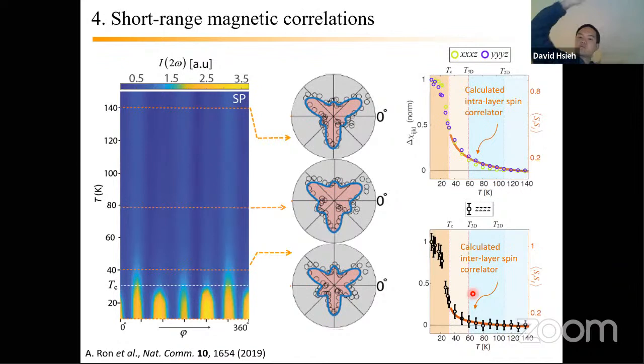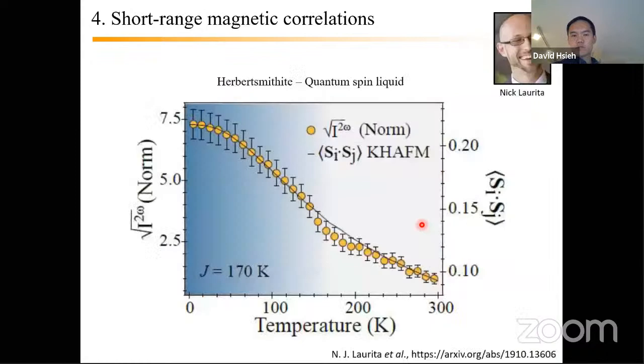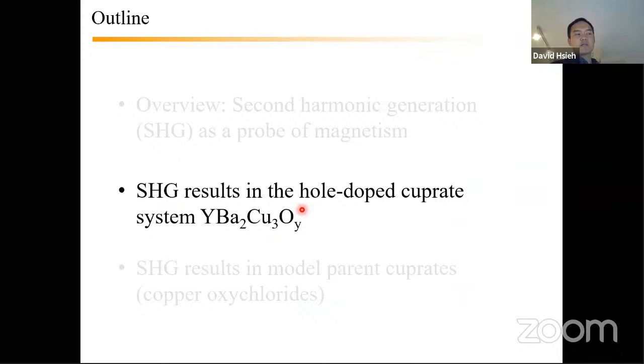Okay, so all that is to say, I'll just flash one more example. That was in a ferromagnet, but even in systems which do not order, like Herbertsmithite, which is a candidate for a quantum spin liquid, we see similar behavior where, across the scale of the exchange, you do see some sort of onset in your SHG intensity. Here, we've plotted the SHG in yellow, on top of, again, a calculated spin-spin correlator. So all that is to say that when you look at our SHG results that I'm about to show you now, this is the critical eye you need to adopt when you start to interpret the data.